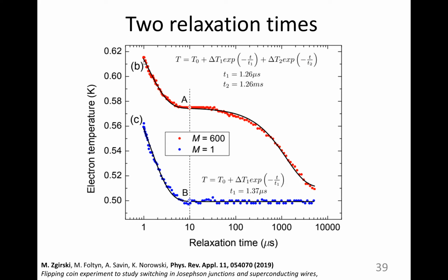But these electrons tend to relax not to the bath temperature, but to the overheated phonon temperature, because the large amount of heating pulses tend to heat up the local phonons, and these local phonons act as a reservoir to some extent for these electrons, and by the time these electrons equilibrate temperature with these phonons, then they can go together to the bath temperature of the sample holder.